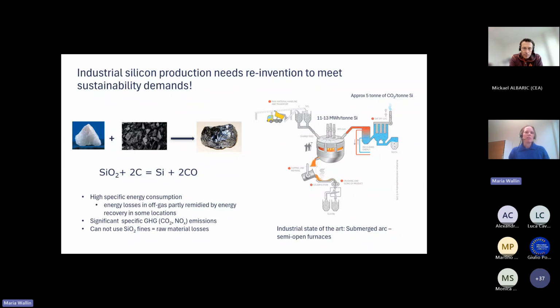And then we capture the off gases. And you see, per ton of silicon, we produce about 5 tons of CO2. So this, of course, needs to be decreased. And also the energy, you see the 11 to 13 megawatt hours per ton of silicon. So we need a lot of energy here. And we also produce fines in this process. So in order to be more environmentally friendly, we have worked on a process to decrease the energy consumption and also the CO2 emissions, which I will mention soon.